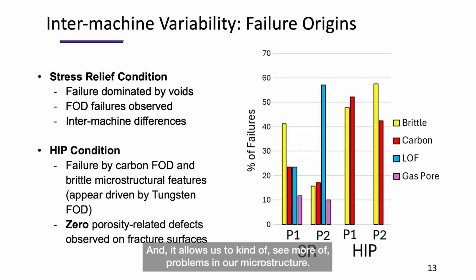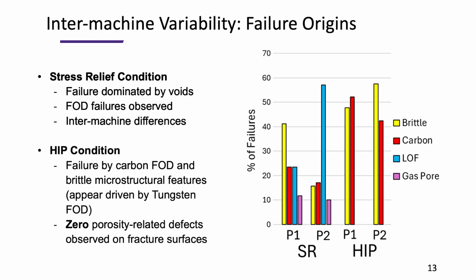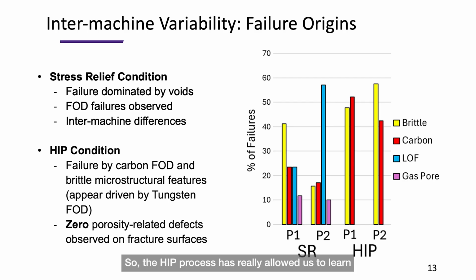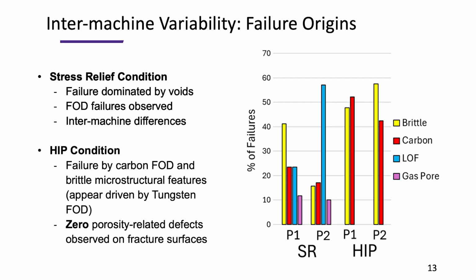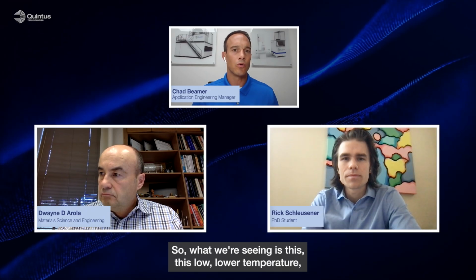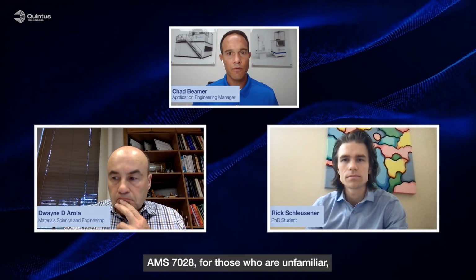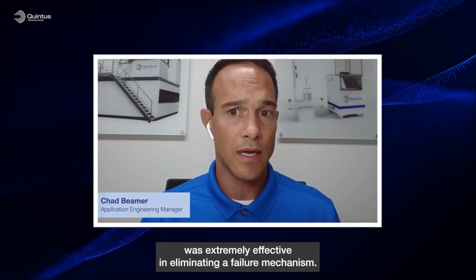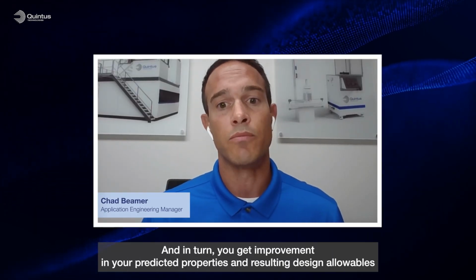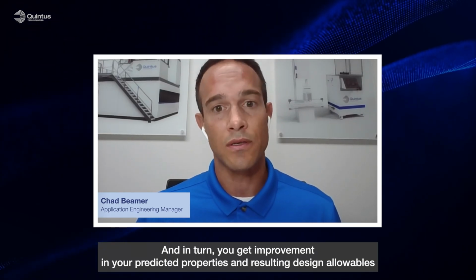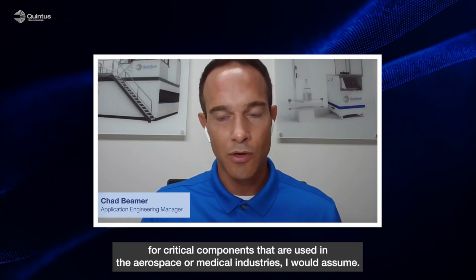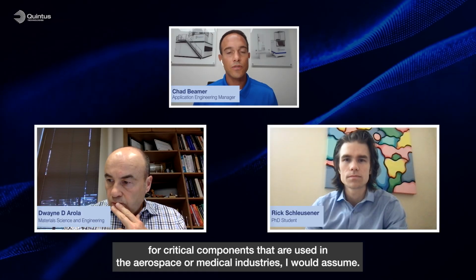And it allows us to see more of the problems in our microstructure. There's a lot more of these FOD failures that are arising because there are no lack of fusion voids present in the metal. So the HIP process has really allowed us to learn more about what's going on in our metal as well. So what we're seeing is this lower temperature, higher pressure HIP strategy, AMS 7028, for those who are unfamiliar, was extremely effective in eliminating a failure mechanism. And in turn, you get improvement in your predicted properties and resulting design allowables for critical components that are used in the aerospace or medical industry, I would assume.